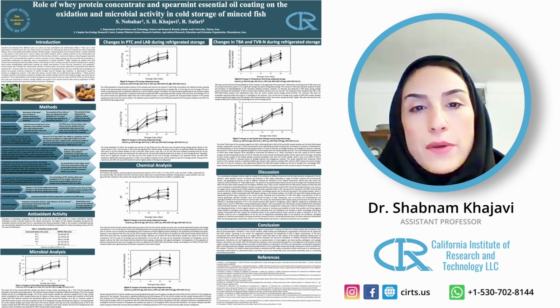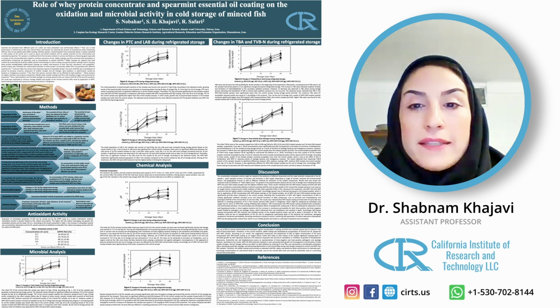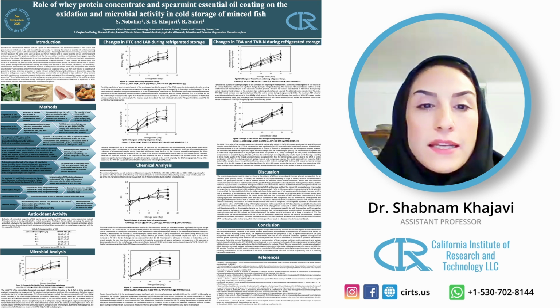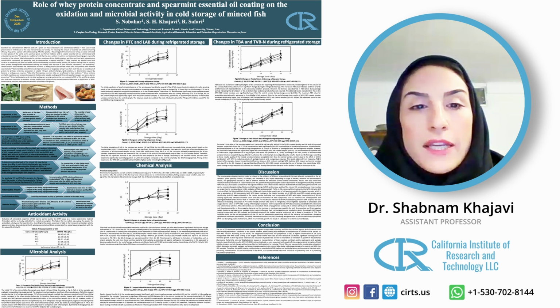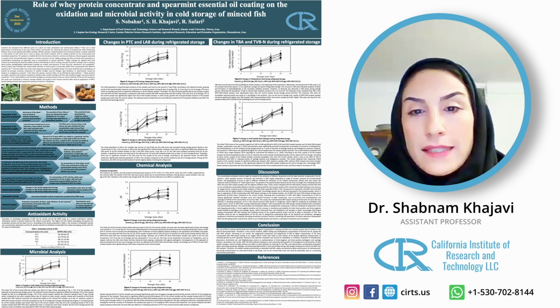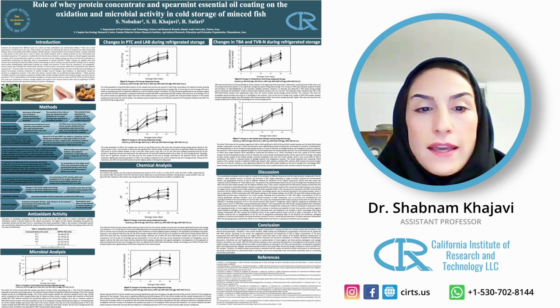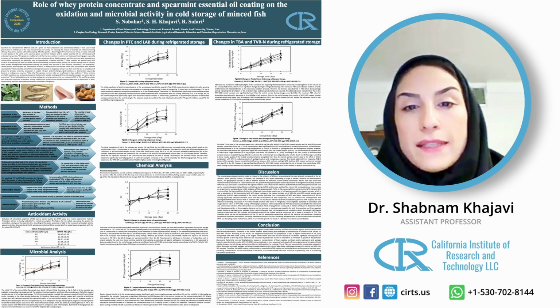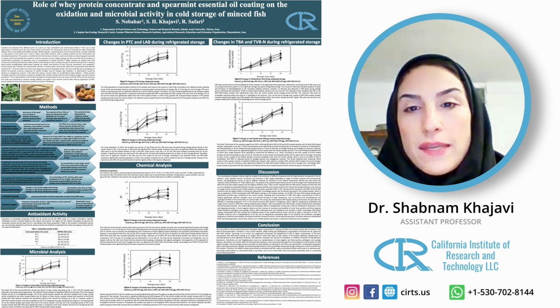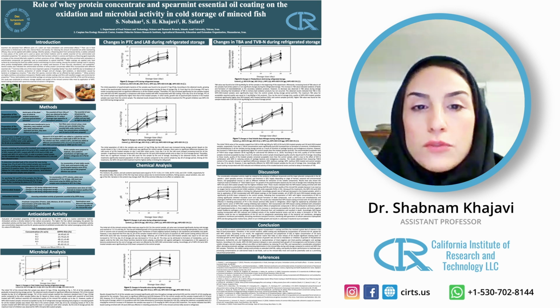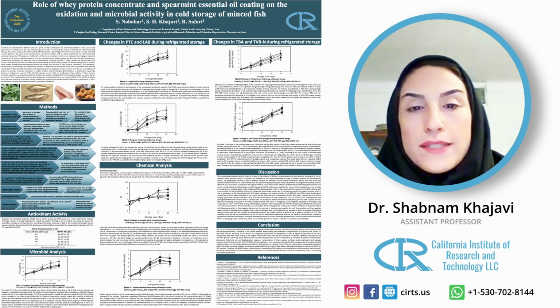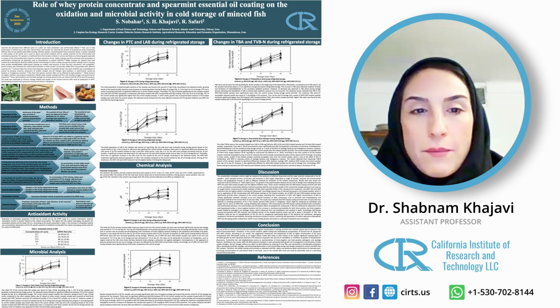According to the results, whey protein concentrate plus 1% spearmint essential oil treatment delayed or even prevented both growth of microorganisms and formation of total volatile nitrogen and pH changes, and with a positive effect on lipid oxidation, reduced PV and TBA, and represented a considerable antioxidant effect, decreasing enzymatic spoilage and preventing deterioration in the minced kilka during cold storage compared to control and WPC-free essential oil samples.